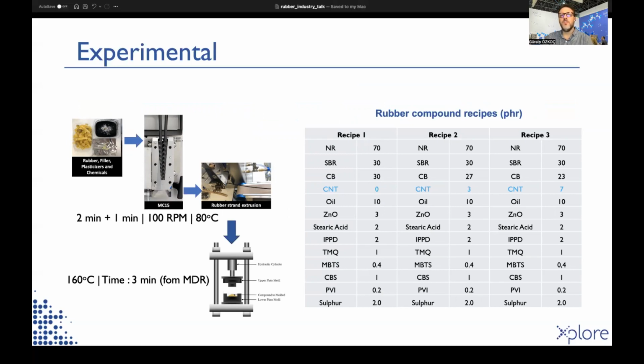We prepared the compounds in a microcompounder, as I already mentioned. The processing conditions are shown here. We only mixed for 2 minutes without the cross-linking system, and 1 minute with the cross-linking system, in total 3 minutes. At the end of the compounding process, the compound was dumped in a mold and cross-linked according to the data which was obtained from moving die rheometer results.